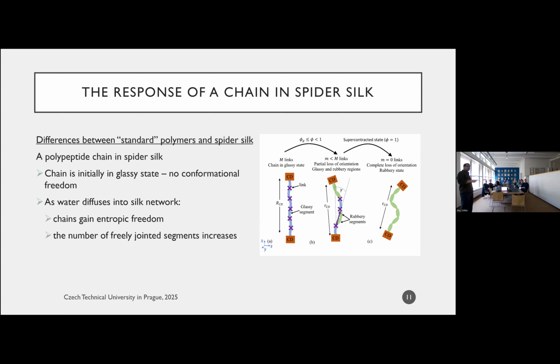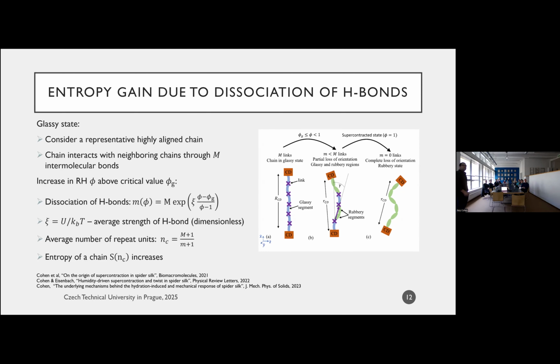And so, if we want to model this, and we want to use the classical polymer physics theory, we have to somehow input all of this information into a model. And so that is what we've done, right? To model the response of an individual chain, let's look at a chain that is initially highly aligned. It interacts with its neighboring chains through, say, capital M intermolecular bonds. Then we propose a relation that tells me how many bonds the average chain has with its neighboring chains. And that's a function of the relative humidity, and it depends on the strength of the hydrogen bonds, or how much energy I need to break the hydrogen bonds. And from this, I can compute the average number of repeat units, and I can compute the entropy.